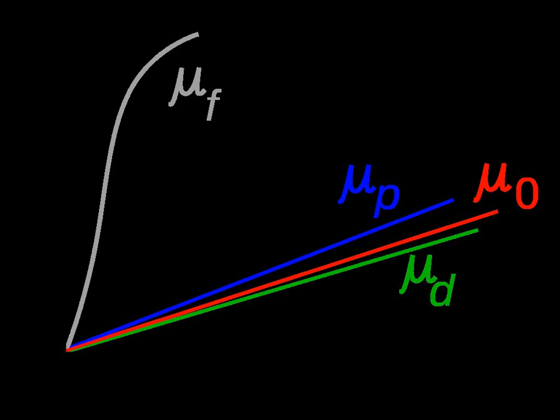The following table should be used with caution as the permeability of ferromagnetic materials varies greatly with field strength. For example, 4% silicon steel has an initial relative permeability of 2,000 and a maximum of 35,000, and indeed, the relative permeability of any material at a sufficiently high field strength trends toward 1.